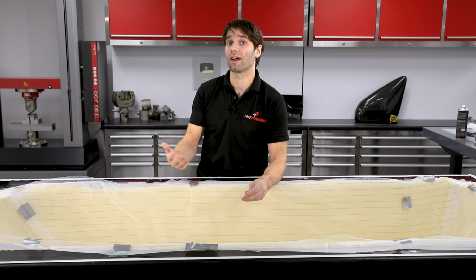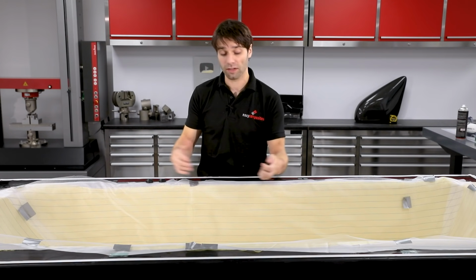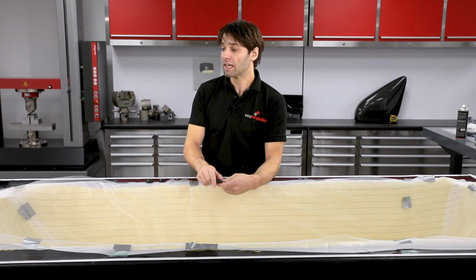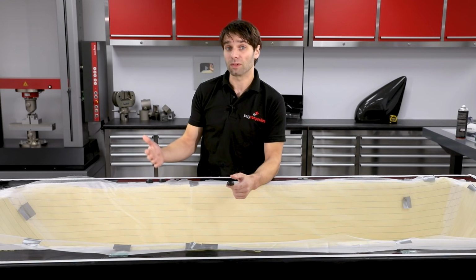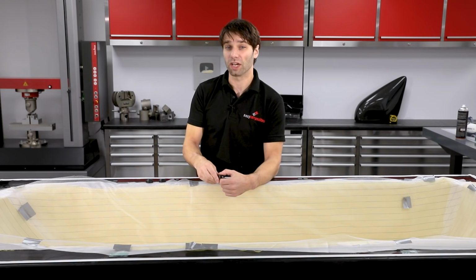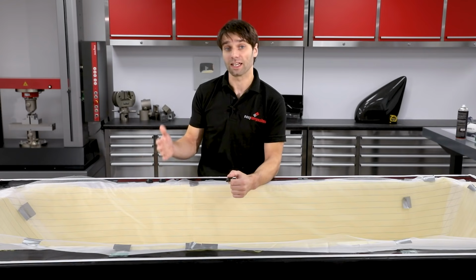So if you had a 10 kilogram resin mix on a very large part, you might need 5 of these. In the case of this part, I think we're going to need 2 inlets because we're going to be running around about 4 kilograms of resin into the part.